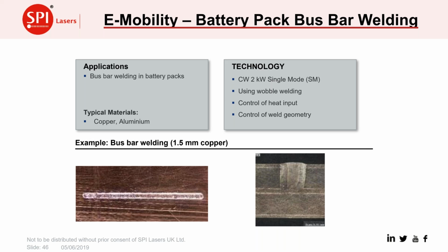Or the two, the copper and aluminium, be joining together. And that's where the advantages come from having the oscillation welding to this. So we control, as we go into the bus bar welding, the depth of penetration and the width of the weld. And obviously the bus bars are electrical current carriers, so the resistivity of any joint is important. And so we can make very high conduction welds using the oscillation welding because we are able to control that weld width and therefore the contact area for the current.